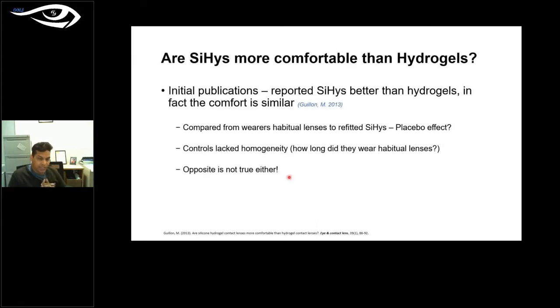So the question obviously is, because now we have silicone hydrogel lenses increasing the oxygen permeability, are they more comfortable than hydrogel lenses? The literature says that initial publications reported that silicone hydrogel lenses are way better than hydrogels in terms of comfort. But later on, the same authors who reported that they were comfortable also reported that the comfort is similar between silicone hydrogel lenses and hydrogel lenses. There are many reasons given for why they were similar. One of the reasons why silicone hydrogel lenses were initially thought to be better is that those studies generally compared wearers' comfort with their habitual lenses, what they were previously wearing.